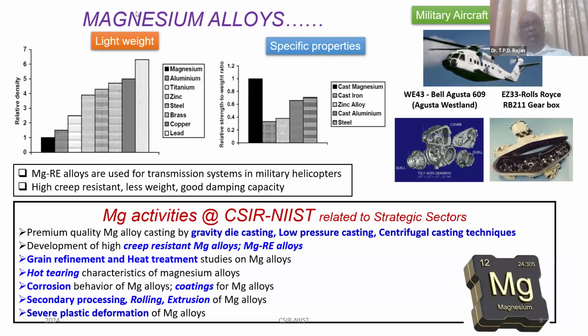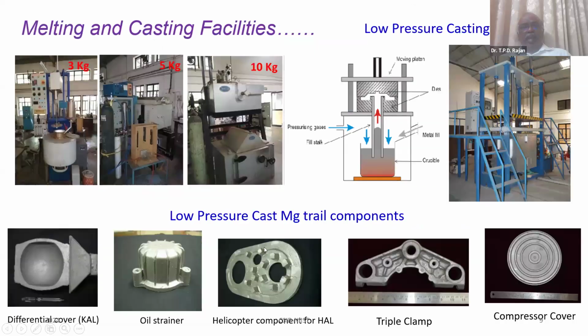And we also work on magnesium alloys, especially rare-earth magnesium alloys. These are being used in the transmission systems of military helicopters. At CSIR-NIIST, we work on premium quality magnesium alloy castings by gravity, low pressure, and centrifugal casting techniques, creep-resistant magnesium alloys, magnesium rare-earth added alloys, and grain refinement studies using different rare metals. Especially our Indian Air Force and others also use the helicopter engine crankcase made with rare-earth added magnesium alloy. This is the magnesium alloy casting facility we have, and we have low pressure casting facilities which can also make prototype components. These are some of the automotive and aircraft components or helicopter components which we made using the low pressure casting facilities at CSIR-NIIST.